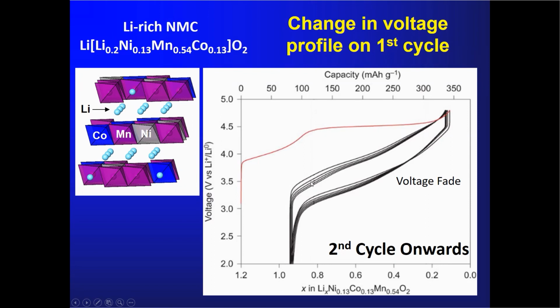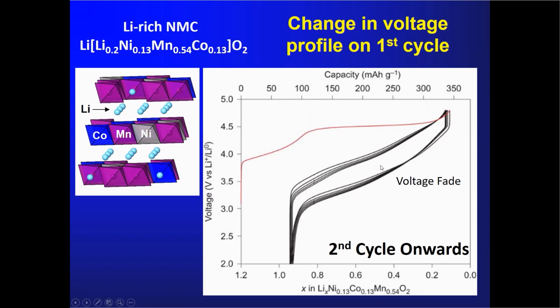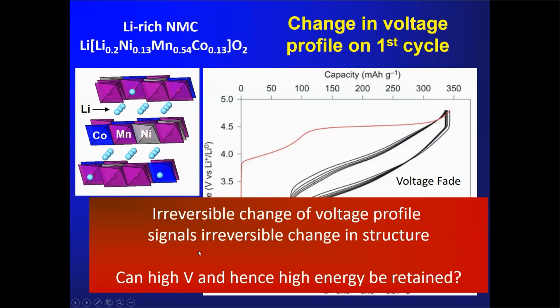The voltage loss, the subsequent cycling at lower voltage, but also you see a change in the voltage curve, which is called voltage fade, and we have to understand this problem. And we have to understand, of course, what's going on in the second and subsequent cycles, as well as this voltage loss on the first one. But a lot of the focus in this part of the talk will be on this large voltage loss and whether we can understand its origin and whether we can stop it happening. So that's simply the point that's made here. Irreversible change in the voltage in the first cycle, of course, signals a change in structure. This irreversible change of energetics, of the energy of the reaction, tells us that something is happening irreversibly to the structure.